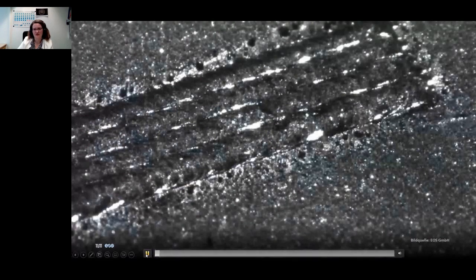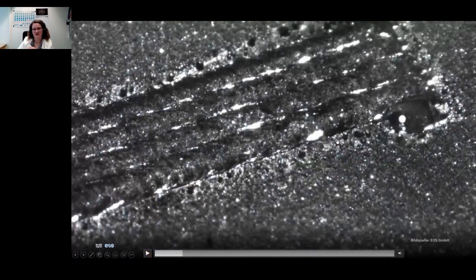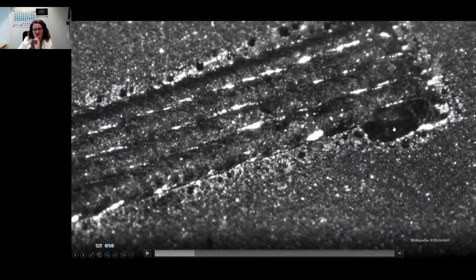And what you can see quite nicely is that we have a really smooth melt pool. We have less spatter formation. It's, of course, a slow motion of the process here.